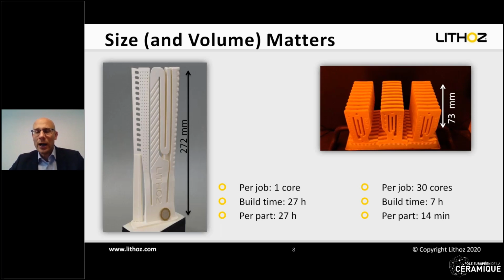Here you see, for example, two casting cores which have been compared. One is a big one with 27 centimeters in height. It takes 27 hours more or less to print this part. But if we go to the smaller cores, we can print 30 cores at once. They are, of course, also smaller in height, 73 millimeters, and the build time per part is then 14 minutes. So what you see, the smaller the parts, the better suited they are for additive manufacturing, because here we have an effect which is different to conventional forming technologies. Here, the less material you're using, the better it is for the price.